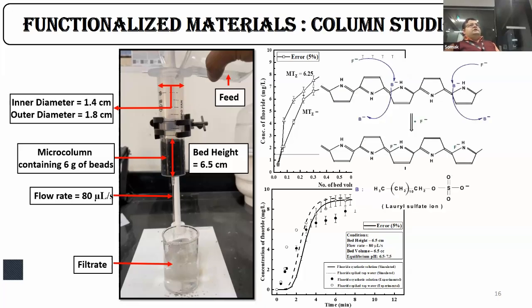After this analysis, we carried out an extensive study to understand the major uptake mechanism. The lauryl sulfate ion present in the conductive polymers plays an important part in exchanging fluoride. The lauryl sulfate ion, being present in the structure of polyaniline, exchanges with the fluoride ions, so the lauryl sulfate ion gets released and fluoride ions get stuck onto the composite polymer structures.